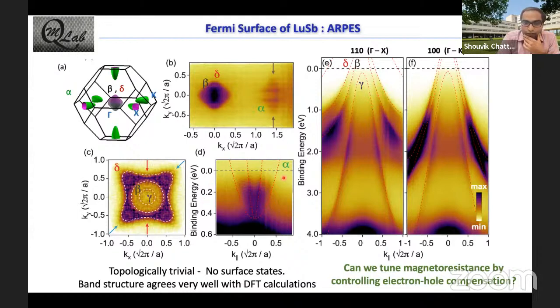And same goes for the electron pocket. You can take a cut here and get an idea about the wave vectors for both the semi-major and the semi-minor axis of the ellipse. So what we find is that it agrees very well with the DFT, and also there is no indication of any surface state, so it is topologically trivial. So what we can conclude here is that yes, in this material system, the magnetoresistance is primarily driven by the electron hole compensation.